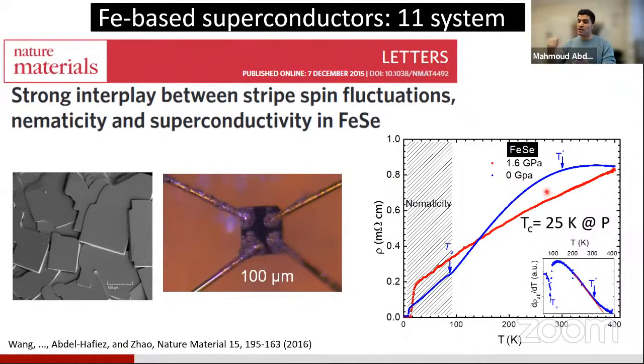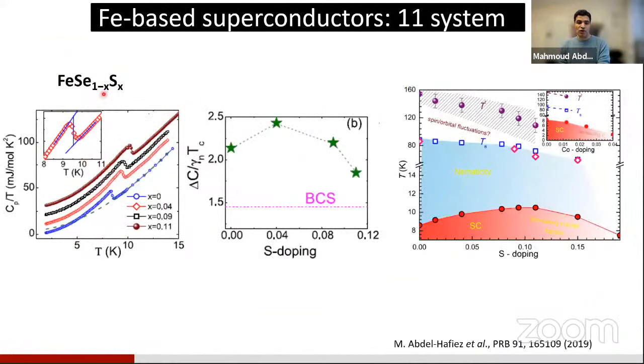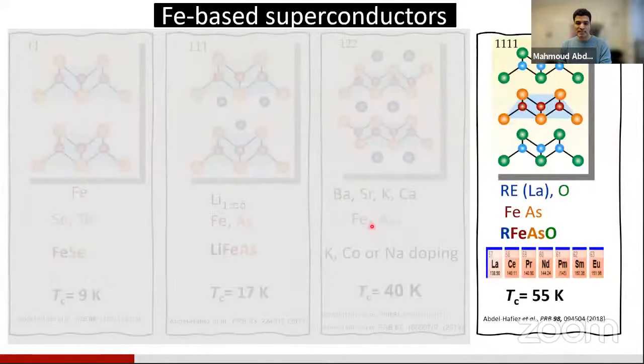Now, what happens if I apply pressure to the system? If I apply pressure, I enhance the TC from 9 to 25 Kelvin, which is also very important for the community, to see how the TC behaves with pressure and also with doping, which I'm going to show now. So with doping, instead of pressure, I try to see whether doping will do the same as pressure. What we can see here is that sulfur doping increases the TC slightly. And this system is not BCS, because in BCS the specific heat jump shows 1.43. And by mapping out the phase diagram, you can see the coexistence between different orders, superconductivity, structural transition and so on. So that was for the 1-1 system.